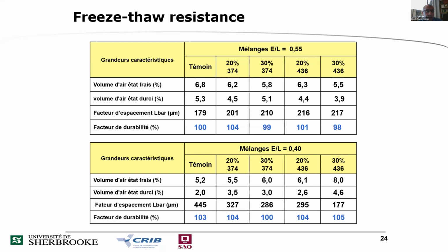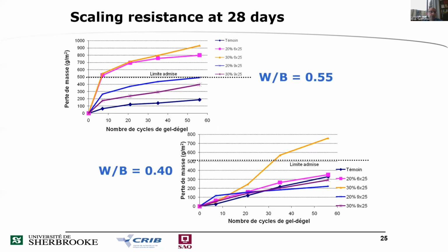Then if you have enough air in your concrete, the freeze and thaw should be good. But it's not the case for the scaling resistance. Even if you have some air, you have a problem when you add some mineral admixtures like fly ash or glass in this case. Then you can see that you are limited to a given percentage of glass for cement replacement.